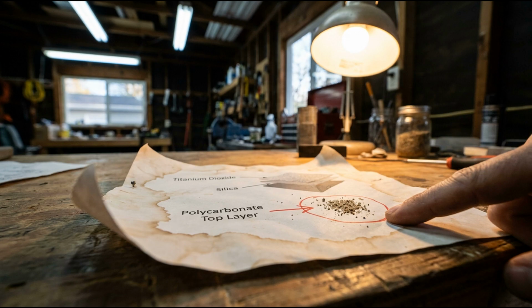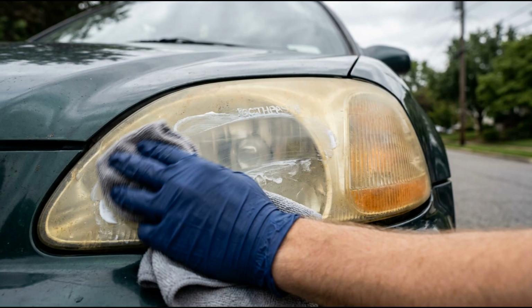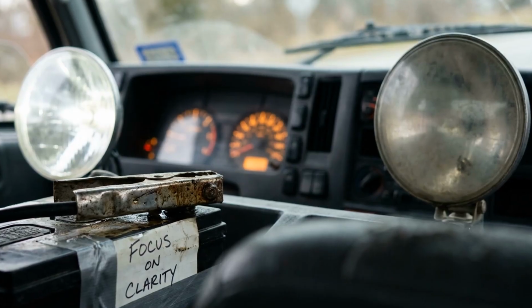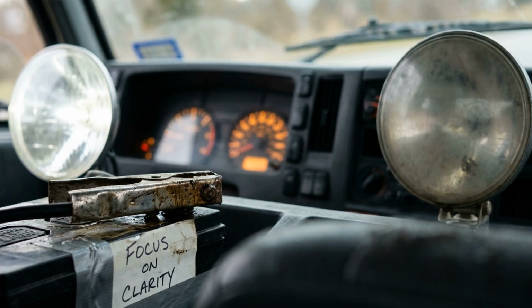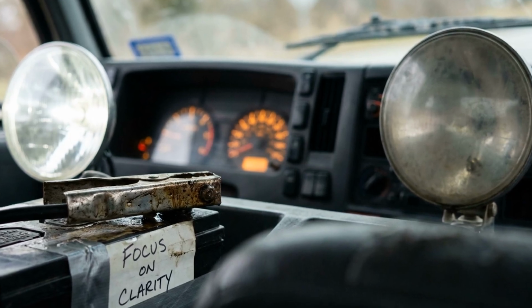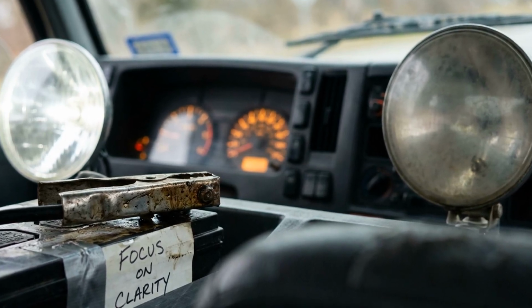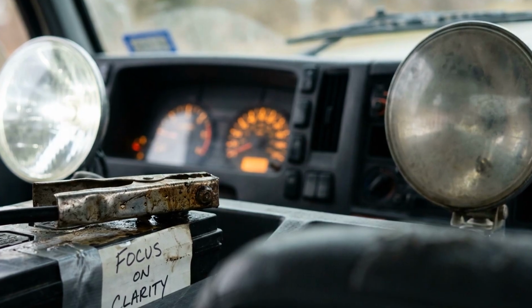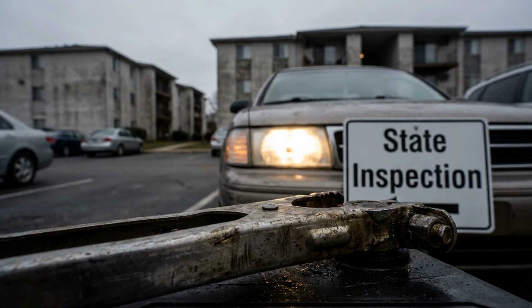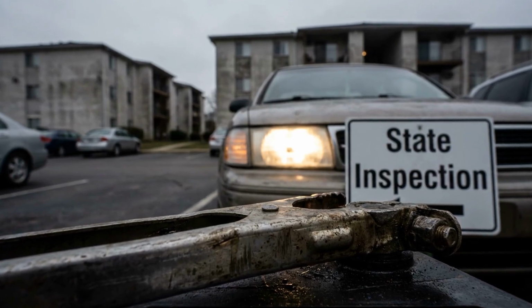Toothpaste contains titanium dioxide, silica, and other microabrasives that polish the top layer of oxidized polycarbonate. Applied with a microfiber and elbow grease, you can measurably improve clarity for 4 to 8 weeks. Then it clouds again because you polished off the oxidized layer but didn't replace the UV protective coating the factory put on originally. The car wax on top is not a UV sealer.